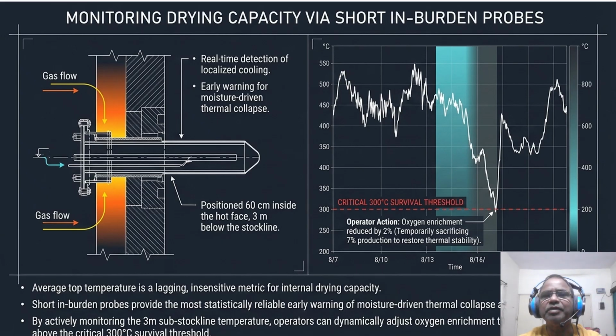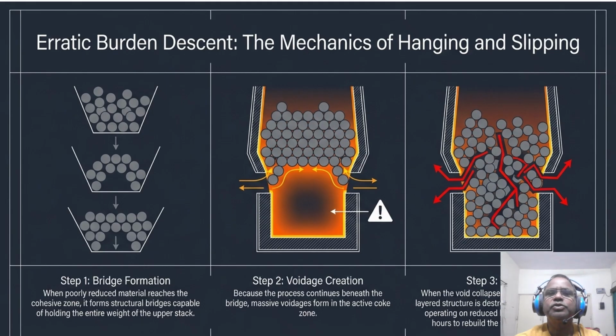So when thermal stability fails at the wall, the physical descent of the burden is the next thing to break. Now coming to the important aspects of erratic burden descent, hanging and slipping now enter the realm of physical irregularities. Now look at step 1, bridge formation. This occurs when poorly reduced material, often due to the moisture issues we just discussed, reaches the cohesive zone and forms a structural arch.